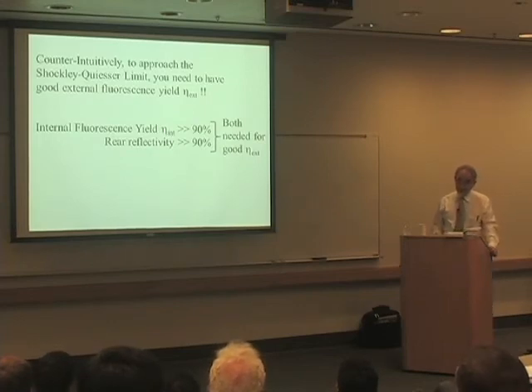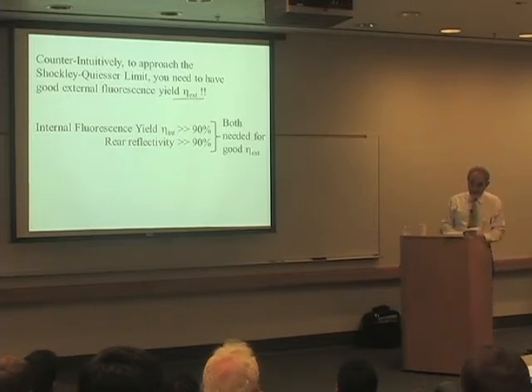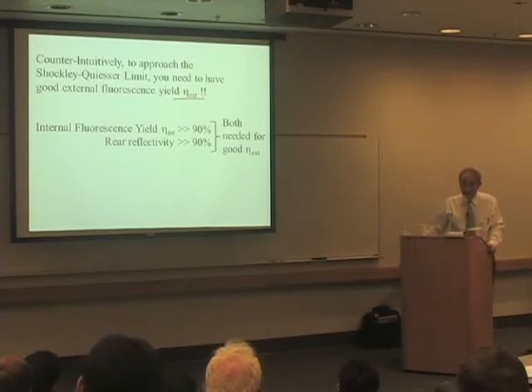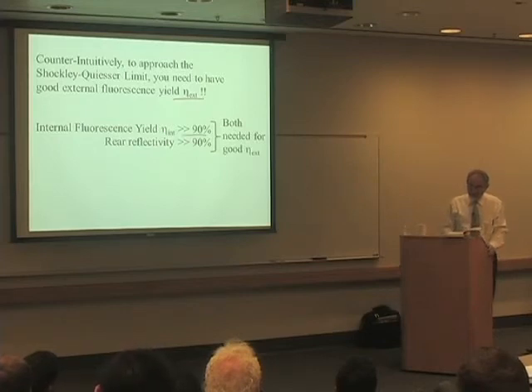Counterintuitively, to approach the Shockley-Quiesser limit, you need to have phenomenal emission. That's very counterintuitive. But the very good external emission is an indicator of very low internal non-radiative losses. And you need to have much greater than 90%, both in the internal fluorescence yield and in the reflector. Both are needed to get good external emission.